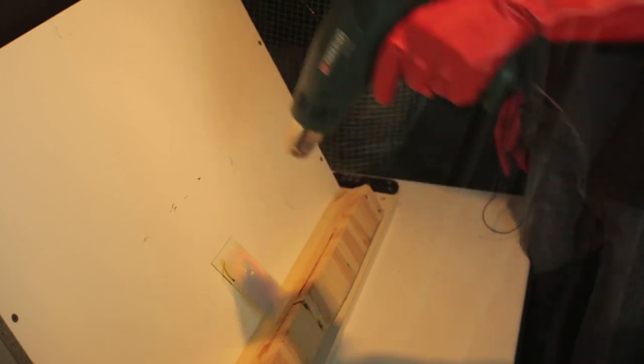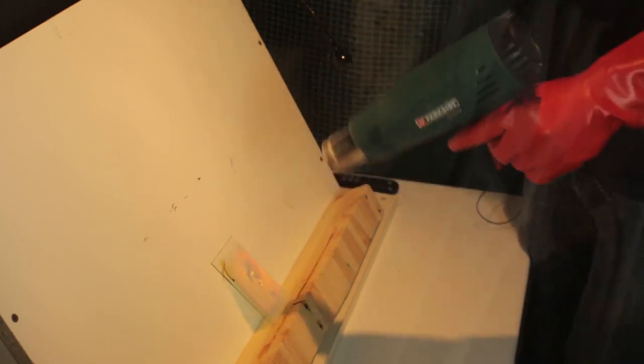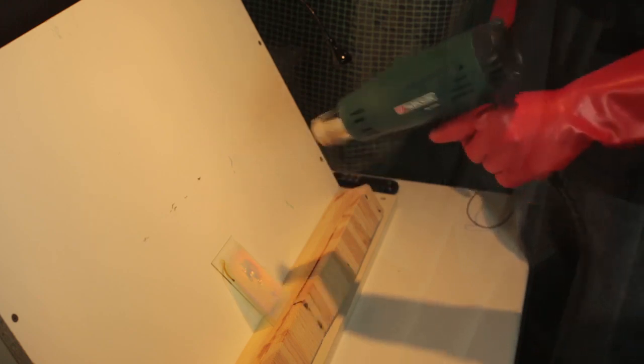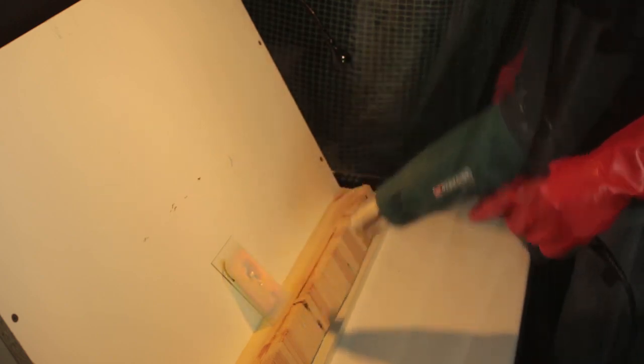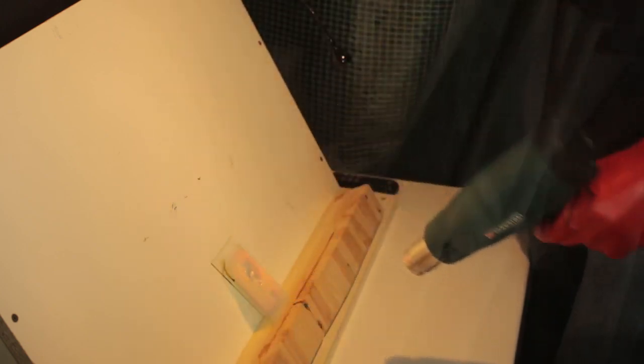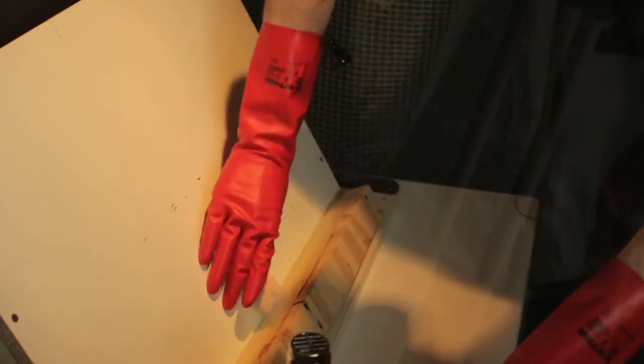After some time performing the L motion, you can concentrate the heat on the middle of the plate, blowing in circles. The plate will become milky at first before turning transparent again. The hologram should appear after 2 minutes of drying. Once I see it, I continue to dry for about another 3 minutes.